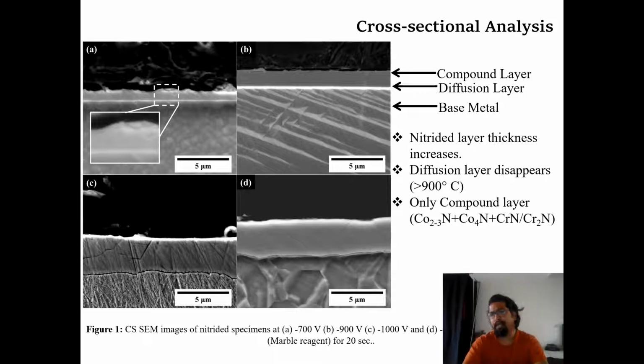The B, which is 900 volt, and here we can see that both the layer thicknesses changed, and now the diffusion layer is thicker than at 700 volt. And later in C and D, you can see at 1100 volt the diffusion layer disappears, and the compound layer still gets bigger and bigger. So the maximum thickness we achieved here was around 5 micron, depending on where we are measuring, and the lowest was 1.3 micron.